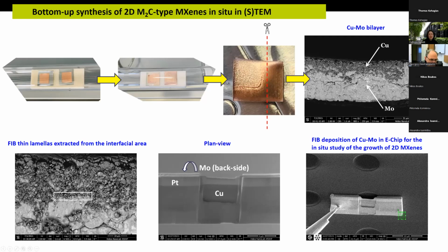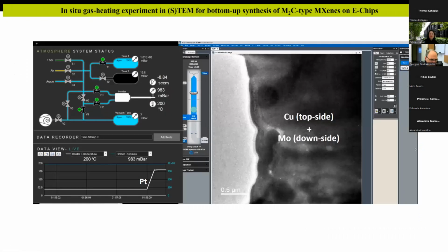And with the help of focused ion beam, we managed to take out a very thin sample of the interfacial area. We further thinned it down. So this part you can see here is an electron transparent region. And then, again with FIB, we managed to successfully deposit our sample on a chip for TEM. These holes here are the electron transparent areas of the chips. And then the fun part started for the in situ TEM experiment.